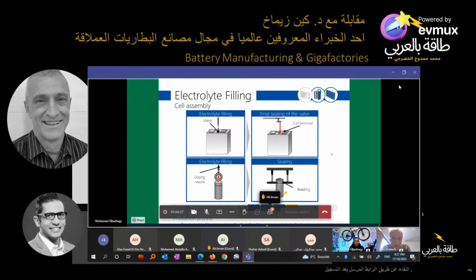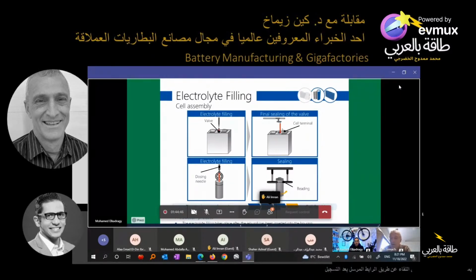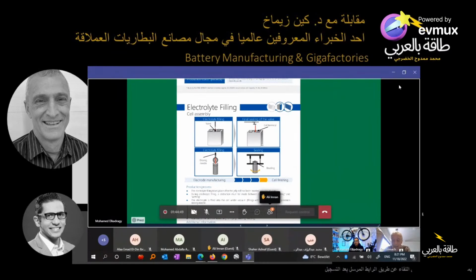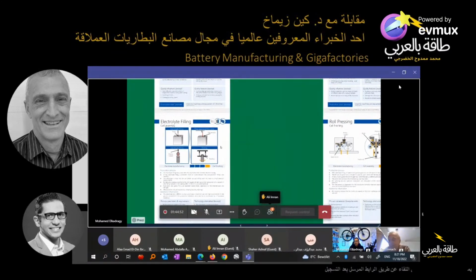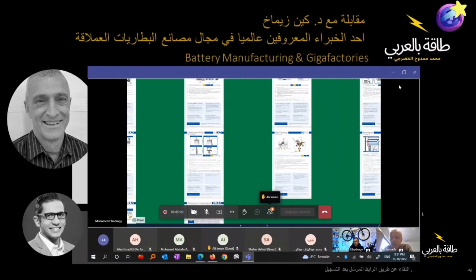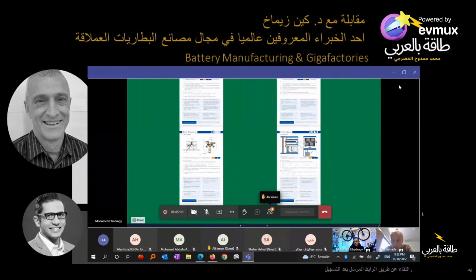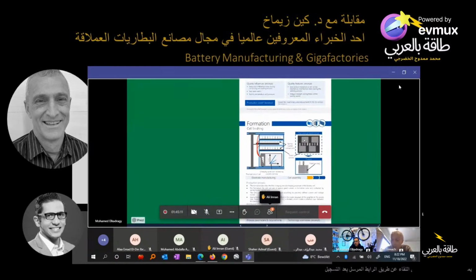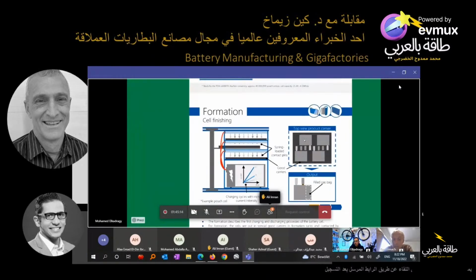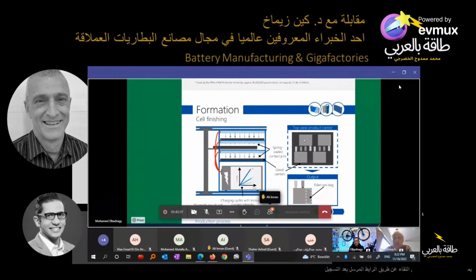Nope, you can't. Usually, before you do the final seal, you do a pre-charge where you charge up your cell a little bit. Depending, sometimes you charge up to a certain voltage lower than full, sometimes you go up to full voltage. Now you're starting the first formation of the cell. You have to make sure all the electrolyte has soaked in. Sometimes soaking can take 30 hours. On large cells, you might have to wait 30 hours at an elevated temperature. Then you do this pre-charge, which is like the first stage of formation.